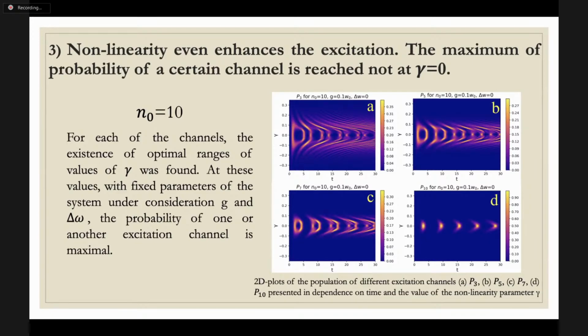For a more detailed analysis, probability distributions were constructed depending on the nonlinearity parameter and time, from which it can be seen that for each channel, you can choose an optimal nonlinearity parameter, at which the maximum probability is realized, even higher than without the nonlinearity. However, for the highest channel, the distribution structure is such that, as can be seen from figure D, it collapses near zero. Therefore, by changing the nonlinearity parameter, it's never possible to enhance this channel, at least simply from the law of conservation of energy.